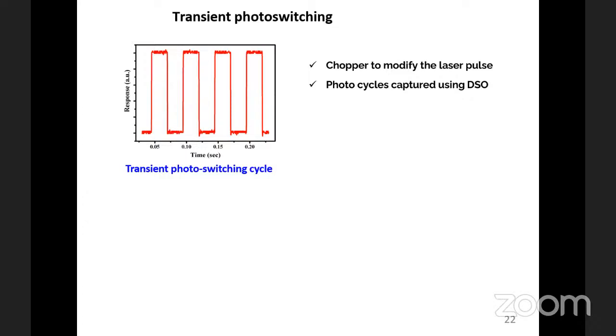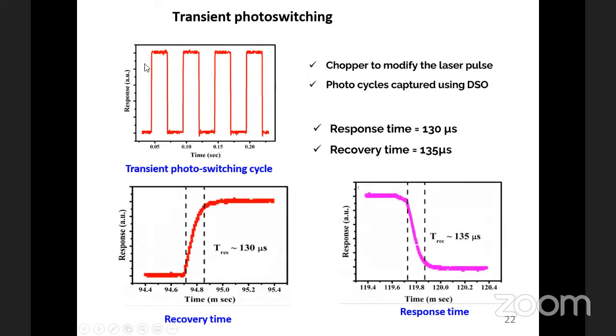In addition, as I mentioned before, the electrons and holes can produce a photocurrent, but in this picture I would like to show you how quickly the generated carriers or excitons can be dissociated, or converted into the photocurrent. This is a special setup I made to analyze these properties. Instead of illuminating with the laser photons continuously, I used a chopper to modulate the laser pulses. I chose a chopper frequency of around 20 Hz to modulate the laser, and the signals were collected using a digital oscilloscope from a single standard modulation cycle. So I calculated the response time and recovery time of the devices.